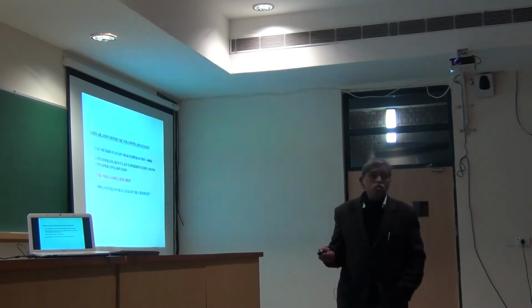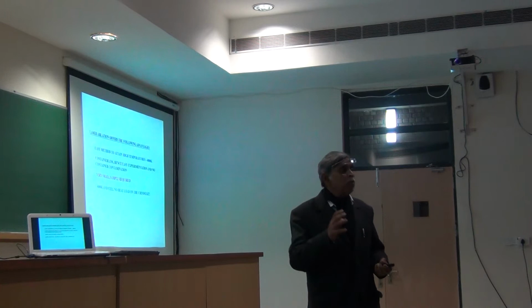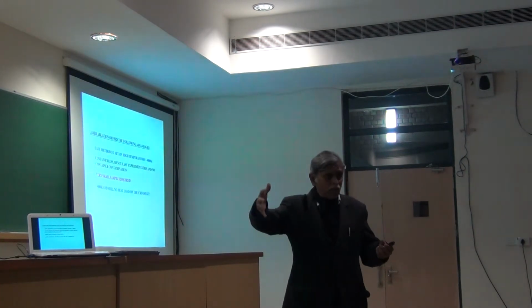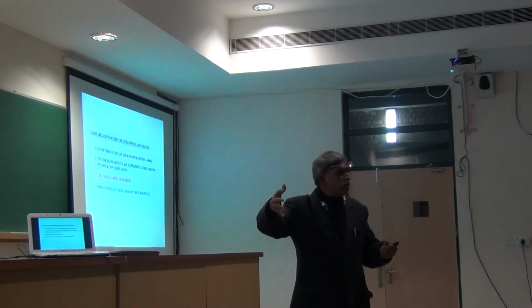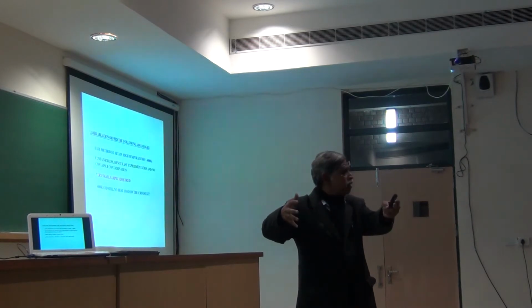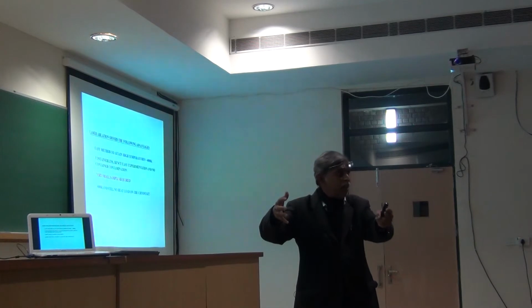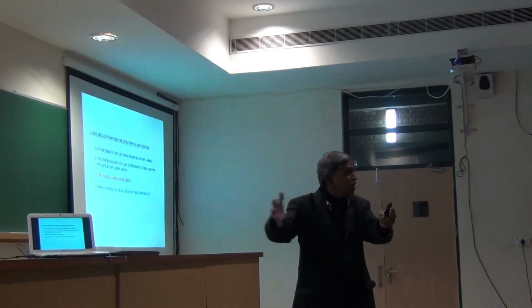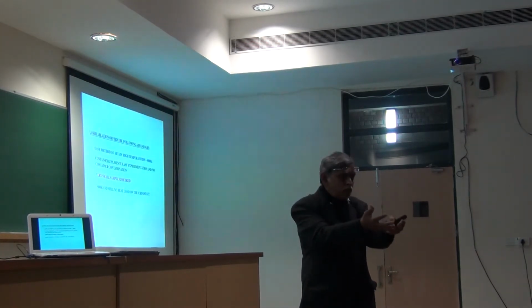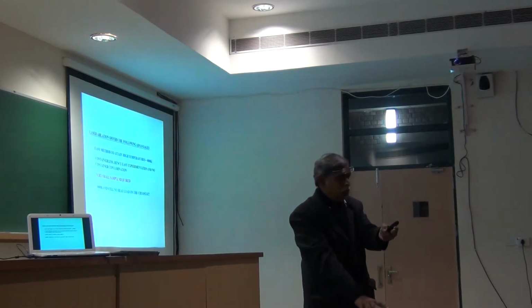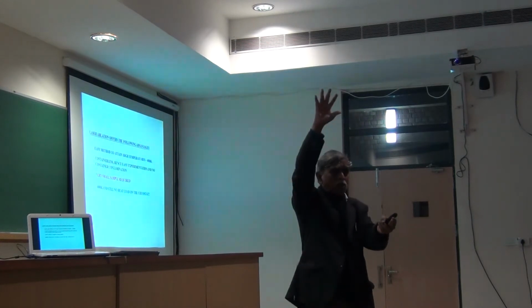It's basically 4000 Kelvin. Just see, this is an experimental model rate. You have 4000 Kelvin on one end, and about 6 inches away, you have a 10K substrate. Now, if I had a furnace of 4000 Kelvin and 10K, this 10K would never get to 10K because the heat load of this would keep heating this up, and this would probably be about 100K or something. Mind, the specific heat is quite low near 0 Kelvin, it just will shoot up in temperature.